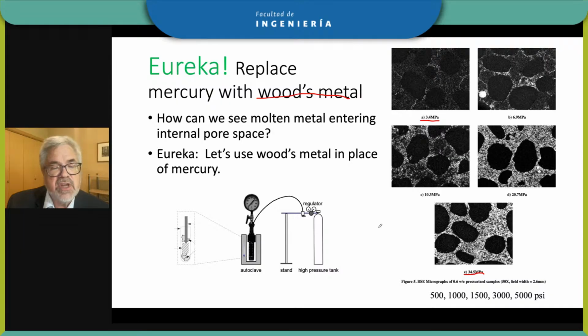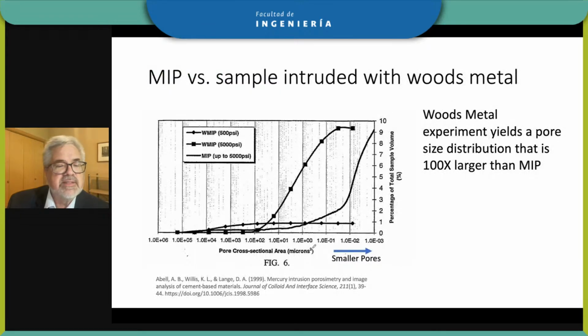So this gives us a chance to get different images at 500, 1,500, 3,000, 5,000 psi using a fairly simple kind of setup with a pressure vessel and an autoclave for heating the Woods metal. By doing this, we can get a result that looks like this. Mercury intrusion shows the volume of pores at different sizes. So does the Woods metal.